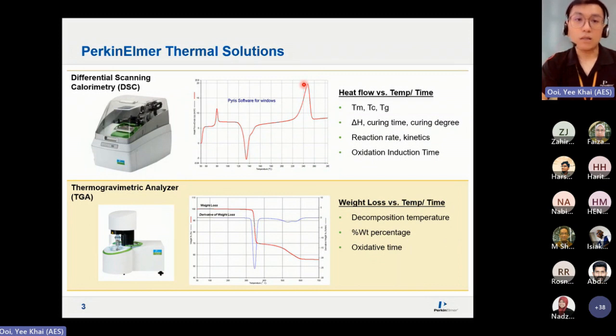So the way we read a heat flow chart or the thermogram from DSC, or if you have an STA, the DTA signals, always read from your y-axis first, because it can indicate endo up or endo down. Make sure your y-axis is in the correct orientation. For example, here shows endo up. That means this is endothermic, this is endothermic, this is exothermic. Because endo up. If endo down, then all of this will be vice versa or inverse. So this is your melting, this is crystallization, this is glass transition temperature.